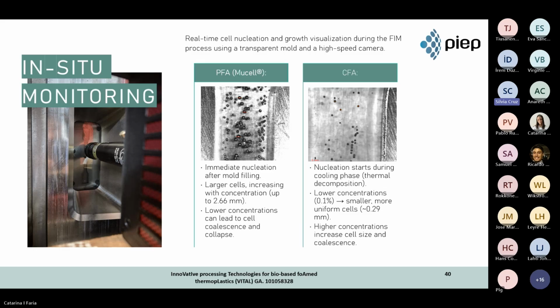By using a transparent mold and a high-speed camera, it was possible to understand how different types and concentrations of foaming agents influence the resulting cell morphology. This information was essential for adjusting bio-based formulations and optimization of injection conditions, minimizing defects such as cell coalescence and collapse.